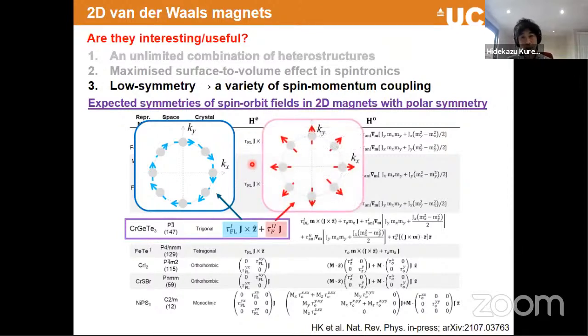Now, on top of it, we can also generate an additional torque. Looking carefully, this direction J is the current direction. That means the effective magnetic field is parallel to the current, and that can draw a simple spin texture like this, a sunflower type. That can be an additional term that can boost this spin-orbit term. Because of the low symmetry, we can generate really interesting spin-orbit terms, and that's the area we can go into and see whether we can maximize these effects to create efficient memory devices.